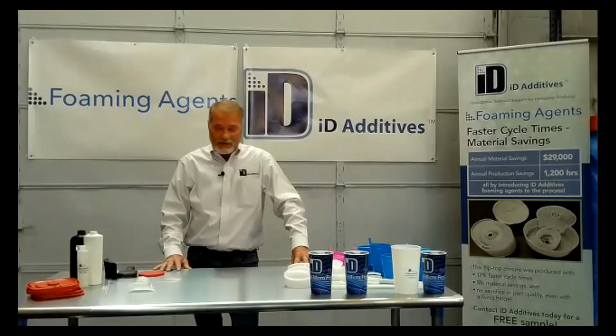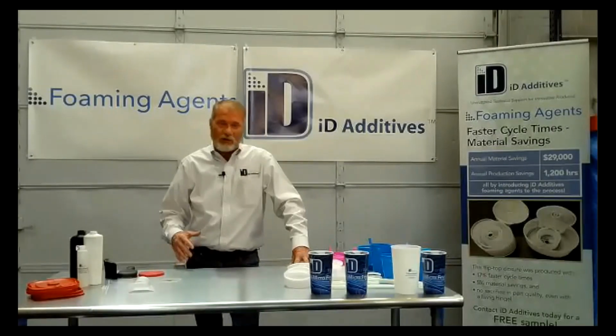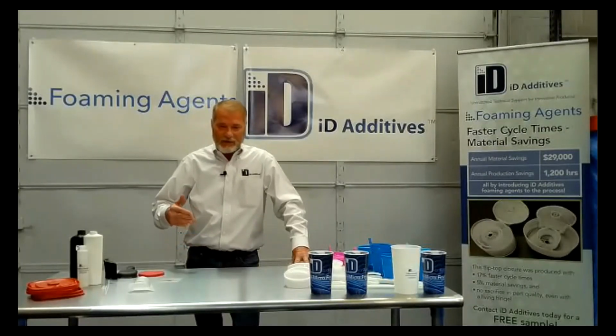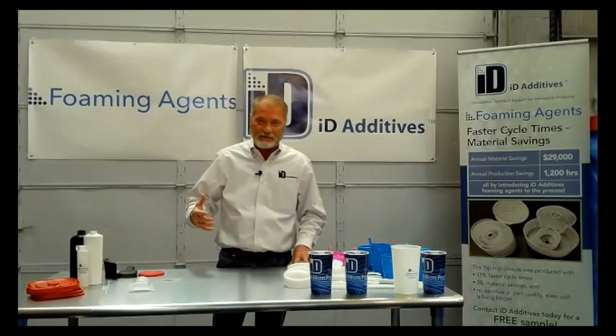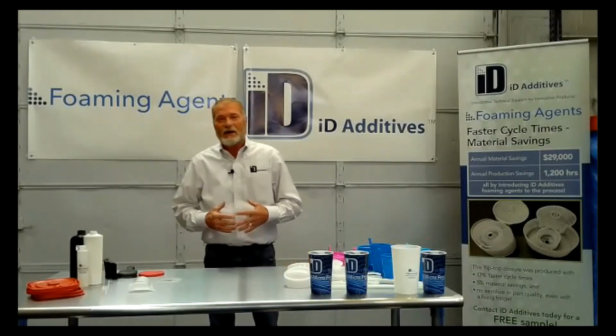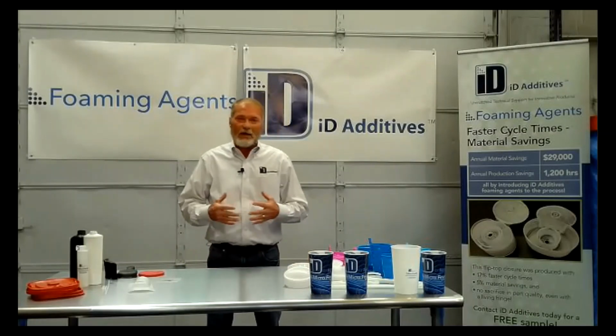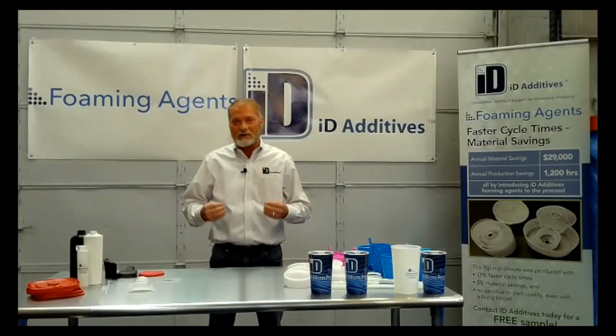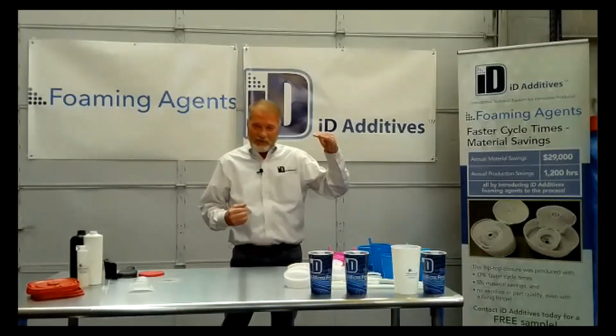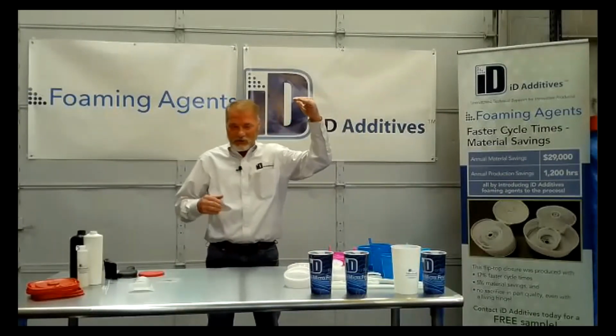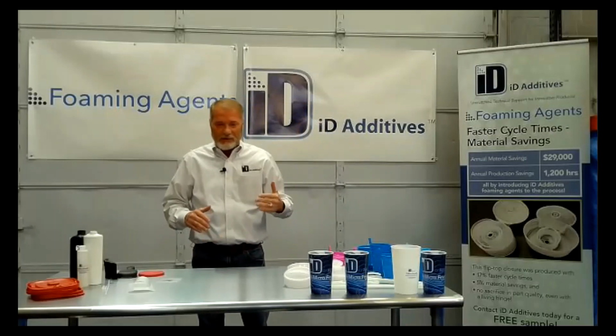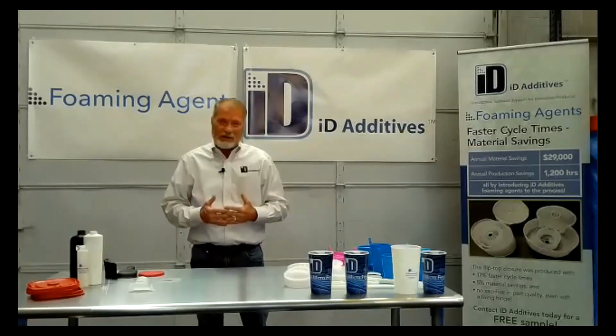I kind of want to get into a little bit of the process and how to control the foam. If you're going to add this product, remember, heat makes it go off. And the hotter it is, the more active it gets. So a foaming agent in most all applications will reduce the viscosity of that material. So always think about, your heat reduces viscosity. The hotter it is, the lower the viscosity. But keep in mind that foaming agent does that as well.